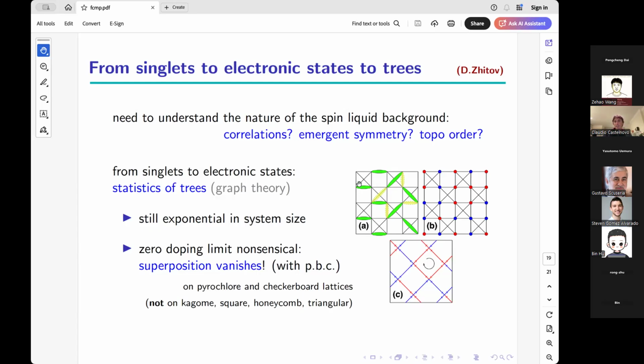However, if we then replace each dimer with a singlet, what were originally orthonormal states become now linearly dependent. And this brings about some issues in discussing the problem that are particularly prominent on the pyrochlore lattice. Ideally, what we would like to do is study the problem without holes and see what the spins do. And then once we understand that spin liquid, we can try to understand how its excitations couple to holes when you remove a spin. However, if you try to follow this route and you take the equal amplitude superposition of all nearest neighbor singlet states on the pyrochlore lattice, that equal amplitude superposition vanishes exactly, which is something that took us by surprise, highly unexpected, because it doesn't on other lattices.